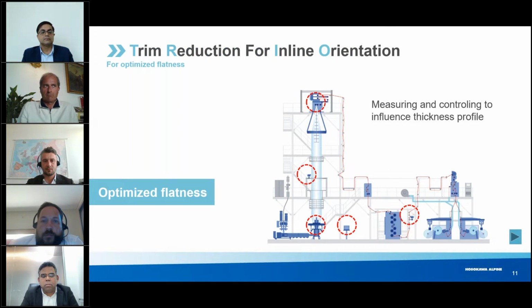First, we will start with the trio system. How the trio system works: you can see here the blown film line, and down here is a sensor that measures the film flatness and gives feedback to the process control. This creates a very flat film, and in addition, where later the edges of the film will be on the winder, 2 atypical thin spots are created here in the cooling ring. This is mandatory to prevent the buildup at the edges later during the stretching process.